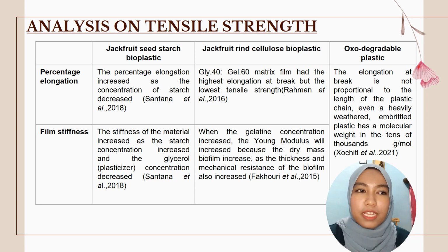For the jackfruit seed starch bioplastic, according to Santana et al. 2018, the percentage elongation increased as the concentration of starch decreased. The stiffness of the material increased as the starch concentration increased and the glycerol concentration decreased. For the jackfruit rind cellulose bioplastic, according to Rahman et al. 2016, the glycerol 40 with gelatin 60 matrix film had the highest elongation at break but the lowest tensile strength. When the gelatin concentration increased, the Young's modulus increased because the dry mass of the biofilm increased, as the thickness and mechanical resistance of the bioplastic also increased.